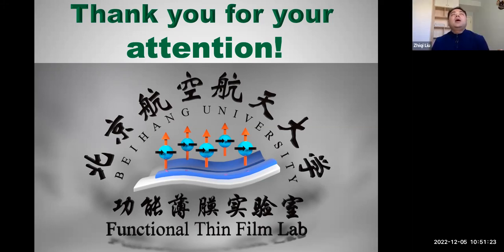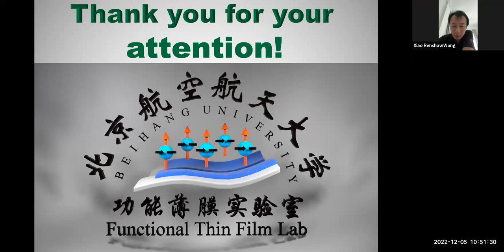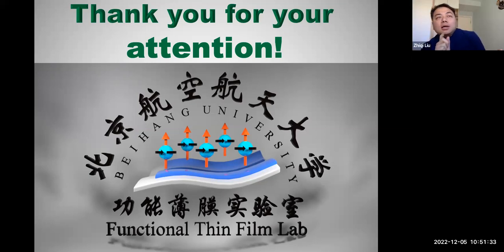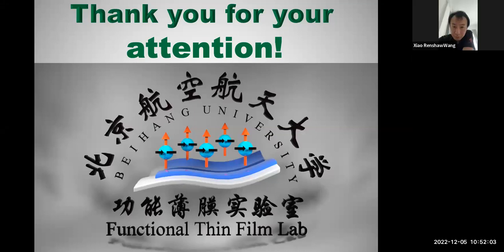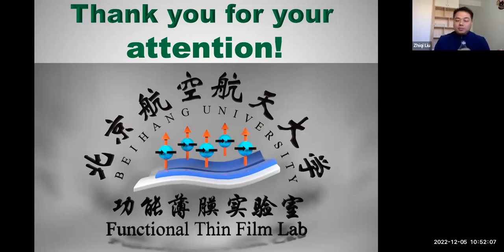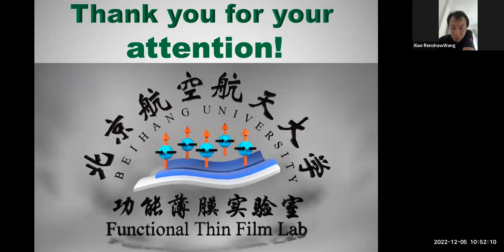I also remember, probably nobody has ever tried to realize layer by layer growth of oxide. I think you still have a chance to try to overcome this difficulty. One way could be you can grow a thin buffer layer of oxide. You can try to grow some ultra thin, for example, 5 nanometer strontium titanium oxide, or a very thin magnesium oxide, MgO layer on top of PMN-PT. That could make the surface smoother. I see. Okay. So any other questions from the audience?